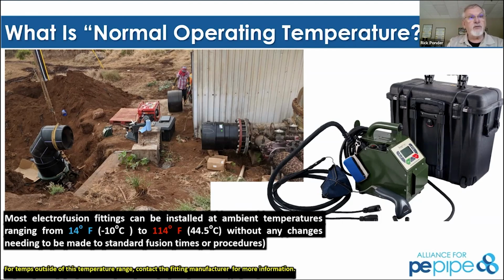Now, it can be fused colder, it can be fused hotter, but in those instances, we basically would like to be called to find out what temperature range, just in the event we may need to modify fusion times or something like that. Yeah, and on the butt fusion side, the standard basically says you should not be fusing below 5 degrees Fahrenheit.